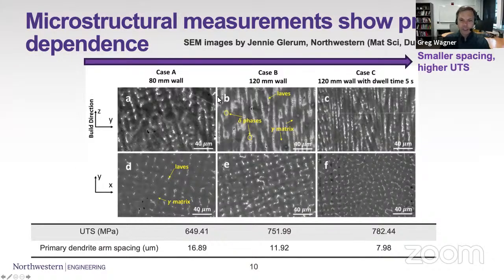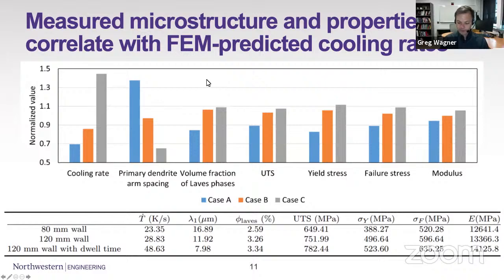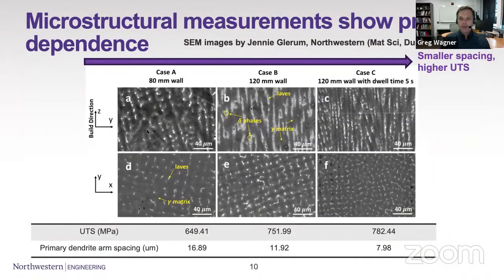that each of these cases, A, B, and C, is a different size wall. Actually, case C is the same size as case B, but with an additional dwell time, so added time in between each scan. And what we see, maybe not unexpected, is that if we measure the primary dendrite arm spacing of each of these cases from these SEM images, we will end up seeing an increase in the ultimate tensile strength. Okay, and we can look at all of the other properties too, but that's one of the main takeaways from this graph. So mostly I just want to show you that we have these images and this data.